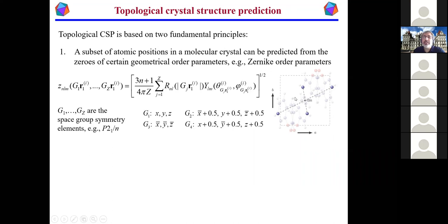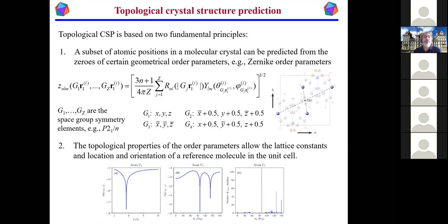And so, for example, if you're doing P21/n, these would be your symmetry operations. You plug them in. Then it turns out that these special positions that we found by mining the database actually turn out to be very sharp minima of these Zernike order parameters for different values of n, l, and m. Okay, so you can see, for example, one of the carbon atoms in my coumarin crystal structure, when you follow it along, let's say, for example, the crystallographic b axis, there's a very sharp minimum at a value of b which is around 5-point-something angstroms, right? So this is now in physical coordinates, not fractional coordinates. Or you can also do it along some of the angles that go into your order parameters, and you can see a couple of very sharp minima appear there.